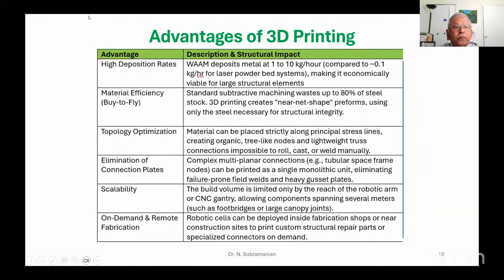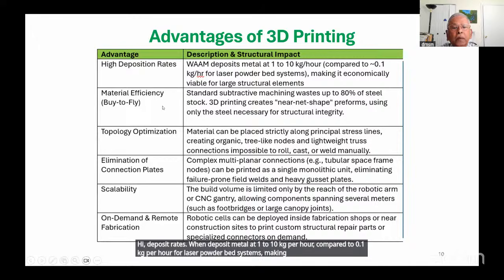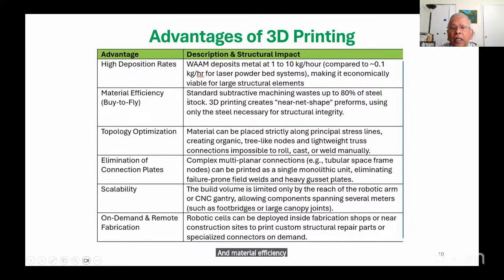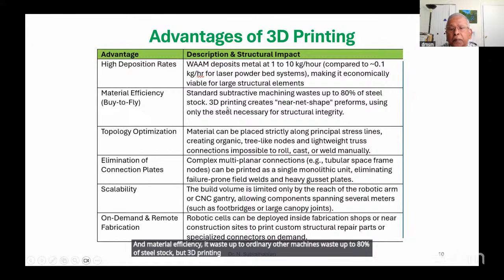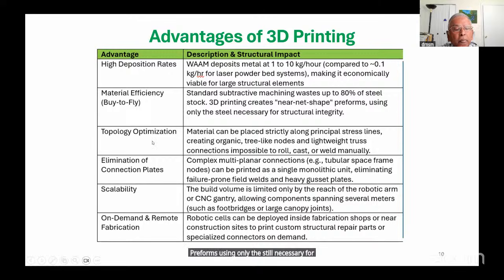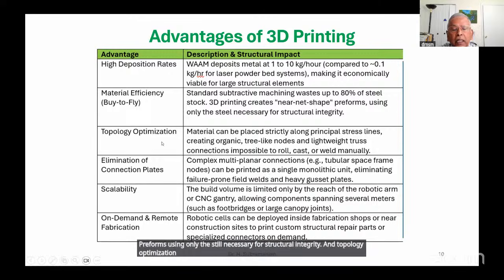The advantages are high deposition rates. WAAM deposits metal at 1 to 10 kg per hour compared to 0.1 kg per hour for laser powder bed systems, making it economically viable for large structural elements. On material efficiency, standard subtractive machining wastes up to 80% of steel stock, but 3D printing creates near net shape preforms using only the steel necessary for structural integrity. And topology optimization, as I already explained, using the software it optimizes.